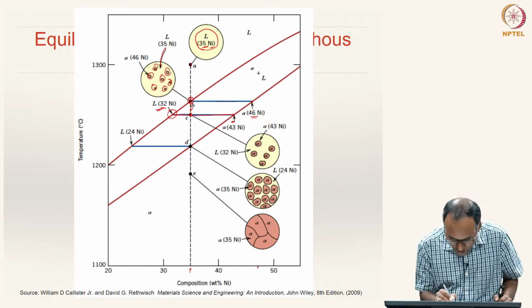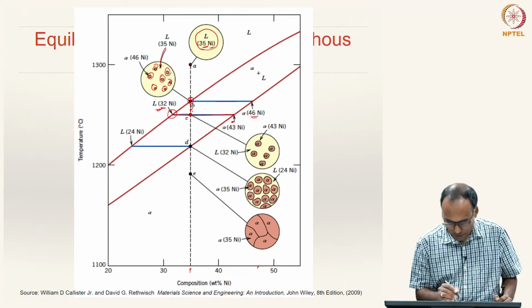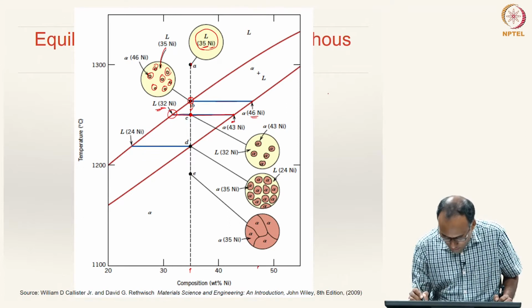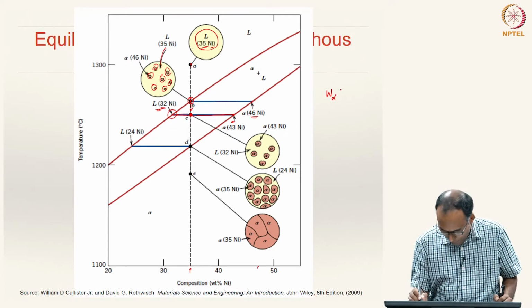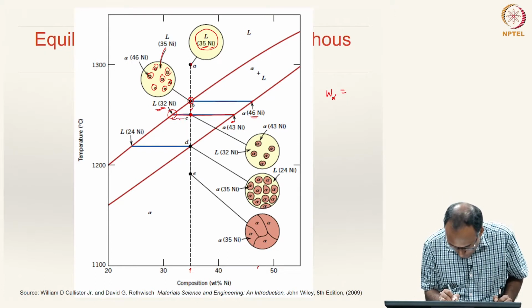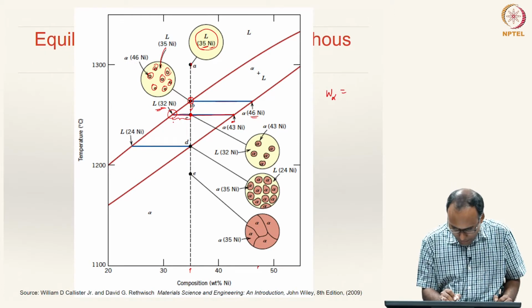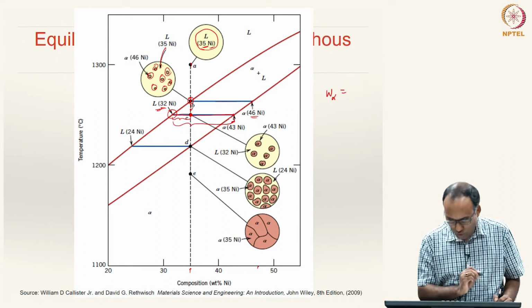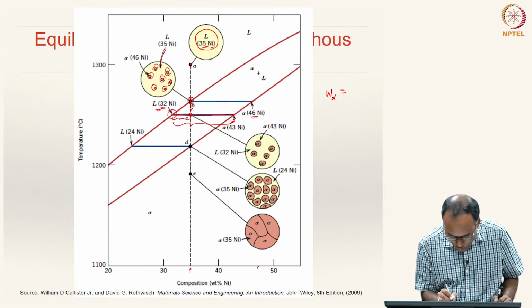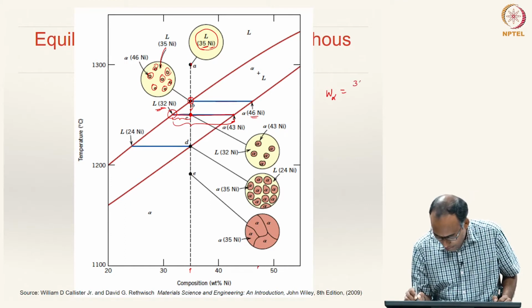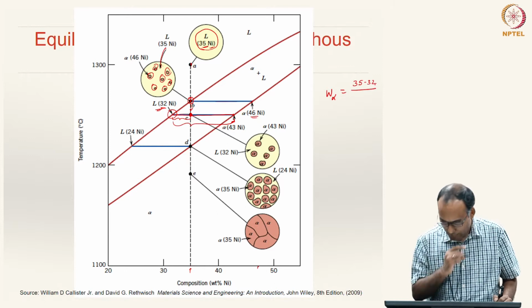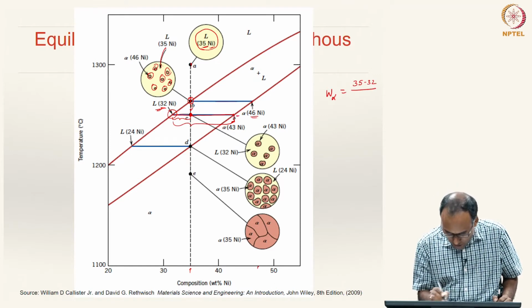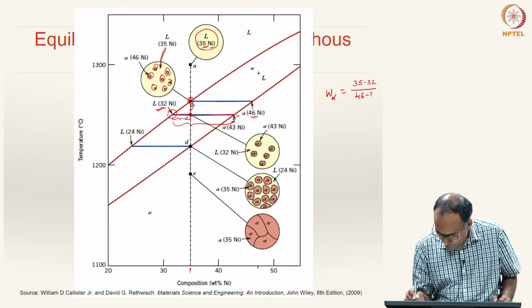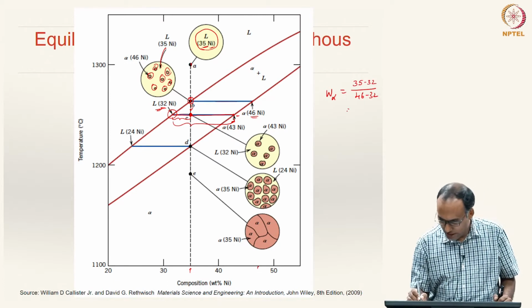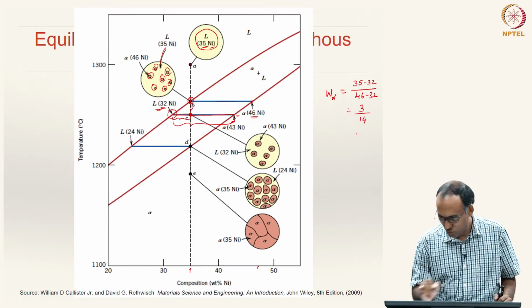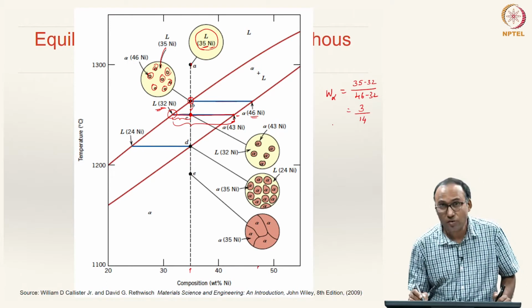What happens to the weight fraction of solid and liquid? What is the weight fraction? The weight fraction of alpha in this case will be this distance divided by this total distance. What is this distance? Here 32 and here you have 35. So, that will be 35 minus 32 divided by, this is 46 minus 32. So, that is 3 divided by 14, that is the weight fraction of alpha.